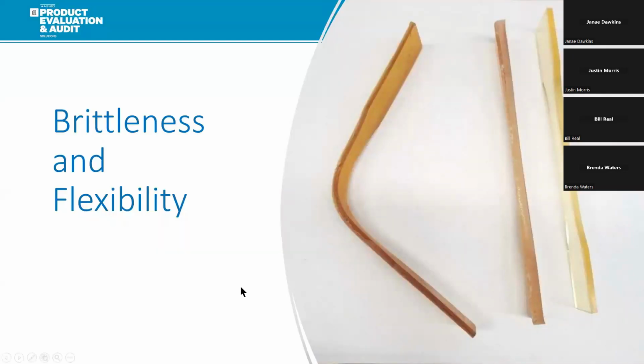Again, what you're going to look for when you're doing your molds and how long it cures, if it doesn't cure properly, you're going to run into some of them that are bendy. That is entirely too flexible. So you don't want to see that. You're also going to see some differences in thickness depending on your mold. So here you have both on the ends are extremely thick. They might be a little bit too thick to put in your equipment, and the one in the middle is a little bit thinner, which will probably be just right.